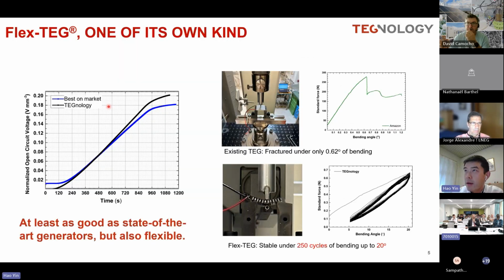With that said, this is a little bit technical, so this is just to show that our flex module is at least as good as the market state-of-the-art ceramic-based bismuth telluride modules, plus we're flexible. To the right, you see the ceramics, of course, it will crack as soon as you bend it at 0.62 degrees. And for ours, after bending at 20 degrees, after 250 cycles, there's no breakage or degradation at all.